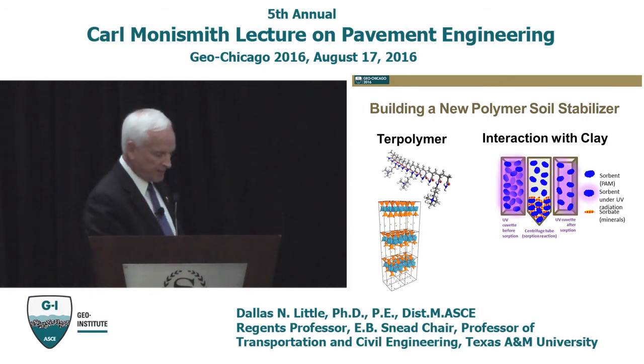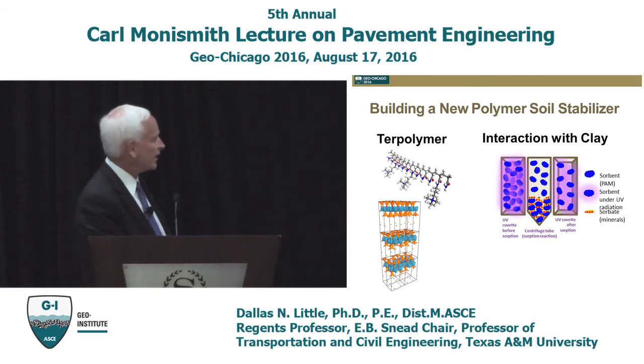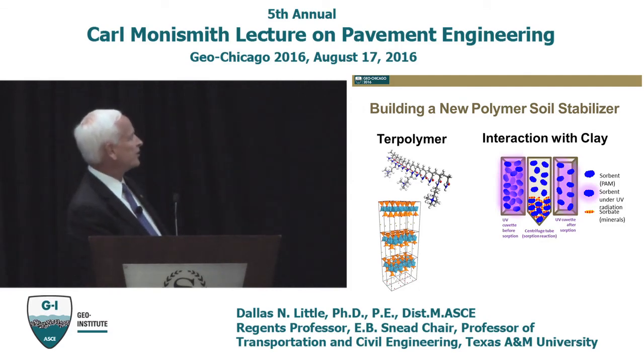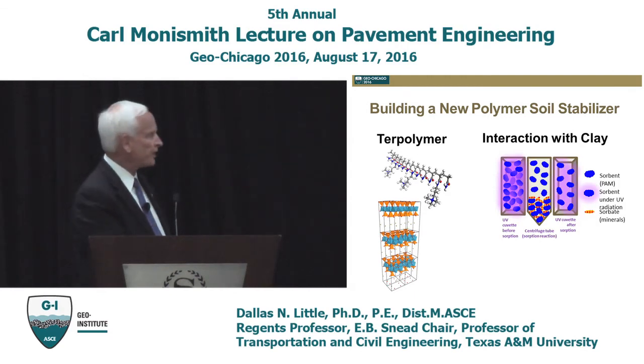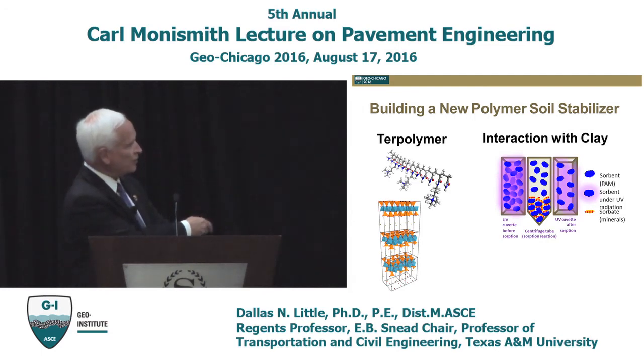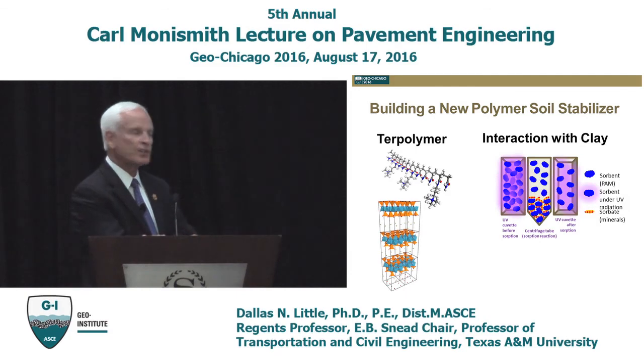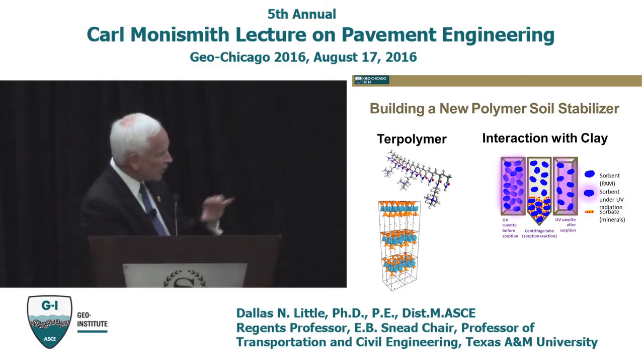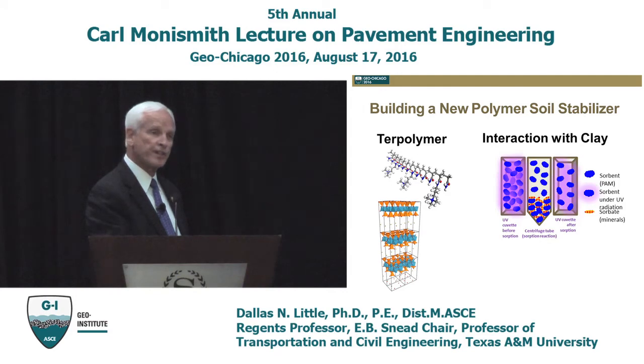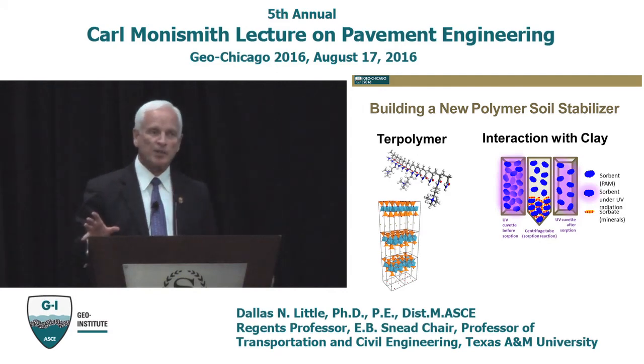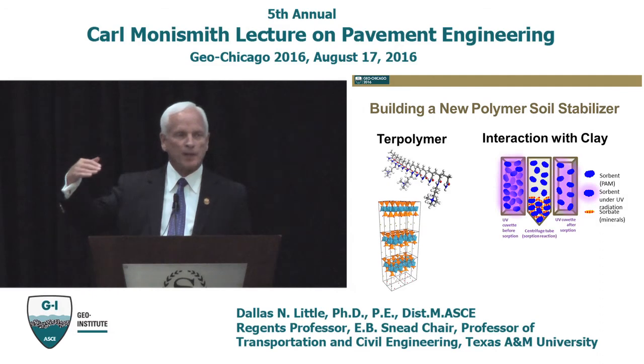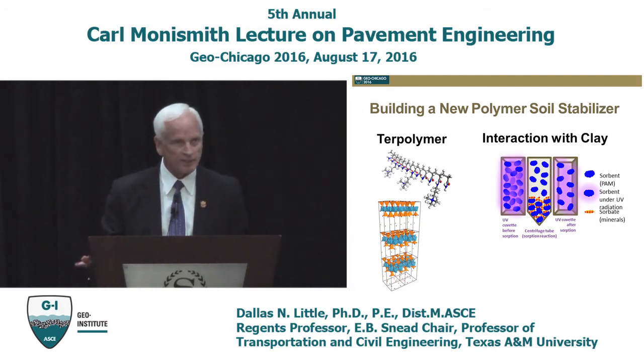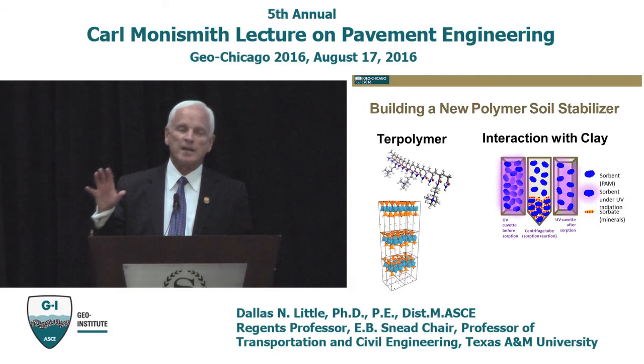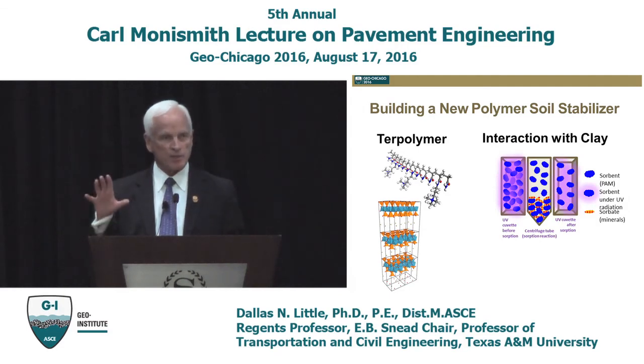And we did some fairly fancy techniques to evaluate that was the process. These particular pictures here are from Dr. Ding over in our soil science area, who's done some work on this in the past. And we were able to see, using the UV vis and X-ray diffraction, that the polymer was able to mobilize into those interstitial layers. And what's really neat about the polymer is that it can give you the same compressive strength as Portland cement, shockingly. But it gives you a much less brittle material.